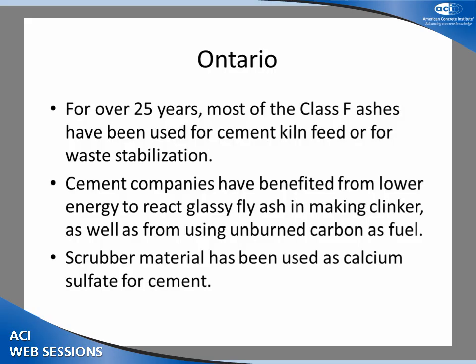So that didn't make it very useful for concrete, but it has been used very successfully, almost 100% of the Ontario ash, as cement kiln feed by the cement industry. If you take a material that's got 12, 15% fuel in it, they're getting free fuel with the raw material. They get their iron, their silica, and their alumina from that material, and the silica is already fused into a glass, which makes it easier to combine in a cement kiln. They actually saved about 15% of their energy by using fly ash as a raw material in the cement kiln. So they've had unit trains running into Michigan. Alpena, Michigan has been converting Ontario fly ash as part of their raw mix for the last 20 years or so, amongst other companies. And it's the cement companies that are largely using the FGD sludges as well as gypsum replacements.